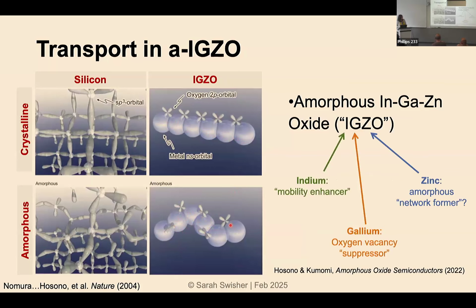So the other thing that's really interesting about this material is that we have this almost infinite space to play with in terms of composition, because IGZO refers to indium gallium zinc oxide. But the indium, gallium, and zinc are really playing very different roles within this material. So the indium you can think of being the mobility enhancer. That's that 5s orbital, and it's giving you higher mobility and tends to give you higher carrier concentration as well. The gallium in indium gallium zinc oxide tends to be what we think of as a suppressor. The ionic bond between gallium and oxygen is stronger, and so it tends to hold the oxygen in the film. And so you have fewer oxygen vacancies, and that way you suppress your total carrier concentration with gallium.